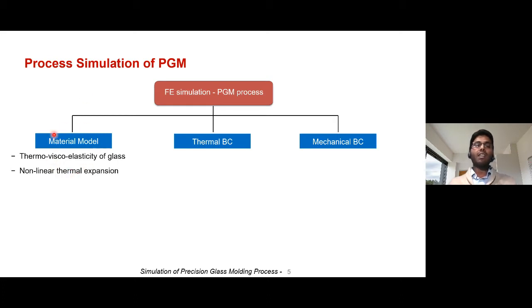So how does the glass behave when the whole pressing operation is being done? At room temperature it is elastic, at high temperature it softens, becoming something like viscoelastic. It has a rate dependent behavior, and then when you cool it, the material transitions back to elastic behavior. So the whole transition is elastic, viscoelastic, and back to elastic. This whole transition has to be captured. So let's look into the material model in detail.